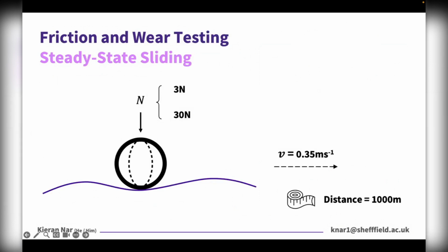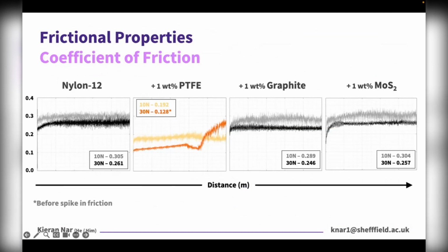Just like before, we performed some ball and flat unidirectional rotational pin on disc sliding tests, which does not get easier to say out loud, on parts produced from each material. What we found when looking at the friction responses was that PTFE was the only solid lubricant addition in which we saw significant modifications in friction.